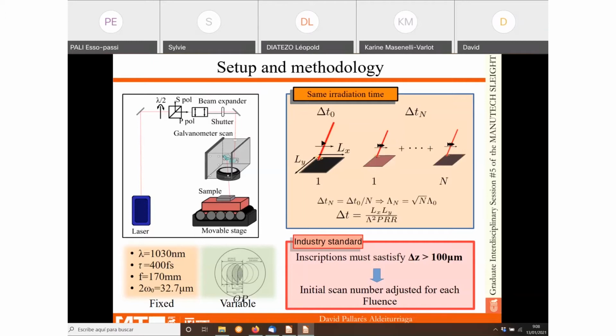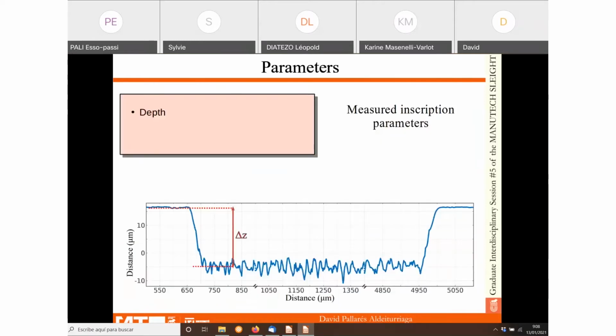So what's the second interesting thing here? Well, as this is applied to the industry, we will be playing with one industrial standard. So we will satisfy the criteria that all the squares should at least have 100 micron depth. And in order to do this, for each fluence, we will set the correct scan number to at least have this depth. Okay. Well, so we have now the methodology, and we start scribbling in the squares.